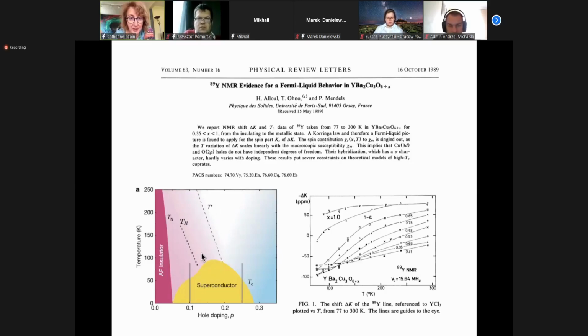So the pseudogap here, what's very unusual, first two things. You have superconductivity close to an insulator, and it's the highest that we have as a superconductor at the moment. And it's close to a magnetic phase, which is also unusual. The pseudogap was discovered in '89, 2 years after these copper oxide superconductors were discovered. Here you see NMR. This is the Knight shift, which is proportional to spin susceptibility. You see a decrease in the Knight shift that those people at that time were able to attribute to a depression in the density of states.